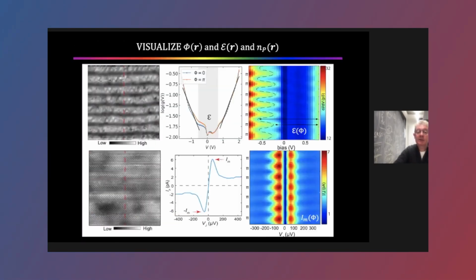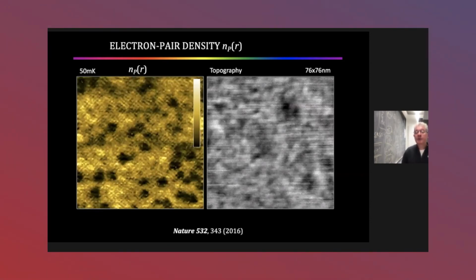So obviously, for many decades, there's been the hypothesis that the condensate of electron pairs in the cuprates is heterogeneous. But when we visualize it directly, it's not. The heterogeneity you see here is due to zinc atoms, which were substituted on the copper site in order to test the technique. And in fact, away from the zinc atoms, the condensate itself is highly homogeneous. So this came as a big surprise to us, and we're still trying to understand what it means. Even though the single electronic structure is heterogeneous, the condensate appears to be homogeneous. But this is now at the frontier of our capability to do scan Josephson. So it's a mystery that remains to be solved.